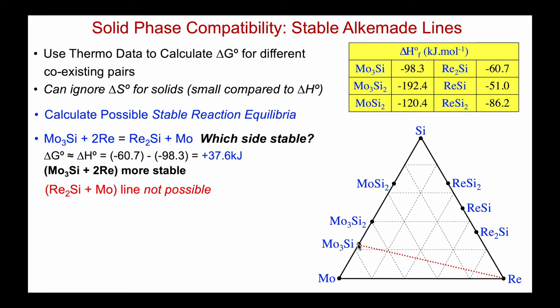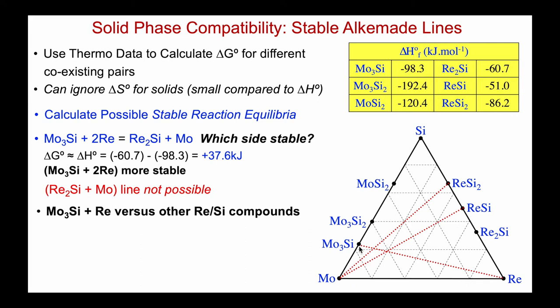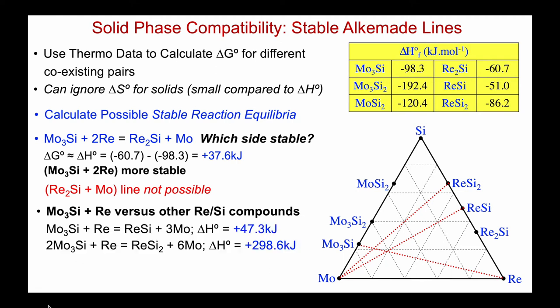So we have our first stable solid-state compatibility line. There are two other possibilities to check. We can calculate whether Mo₃Si plus Re is more stable than ReSi plus Mo — delta H is positive, indicating the left side is stable, so our original line holds. We can also check Mo₃Si plus Re against Mo₃Si plus ReSi₂ — again, enthalpy is positive. So we know Mo₃Si–Re is definitely a stable Alkemade line, and we can get rid of those other two possibilities.